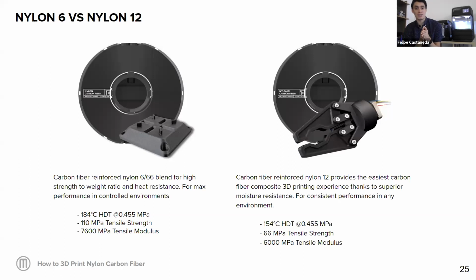Initially, we introduced our standard nylon carbon fiber. And it's actually not just nylon, but a nylon 6/66 blend for an incredibly high strength to weight ratio and heat resistance, right? It's super strong. The heat deflection temperature is way higher, actually higher than nylon 12. It goes all the way to 184 degrees Celsius, has 110 megapascals in tensile strength, and the tensile modulus is way stronger. However, nylon 6 is much more sensitive to humidity changes.